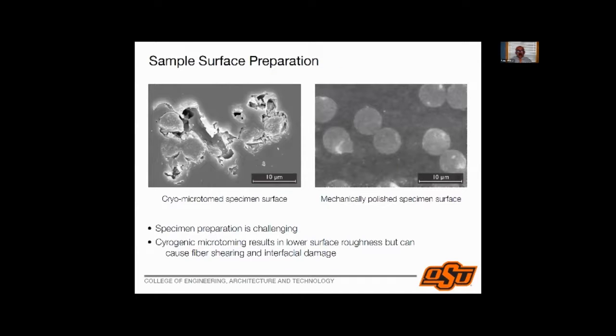Okay. The specimen preparation is very challenging. On the left, you see an image which was cut through with a cryomicrotome, and you can see that the interface is damaged. On the right side, we see a mechanically polished specimen surface. So when we do AFM mapping, we have to make sure that we are polishing these.